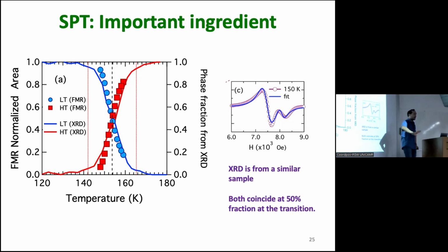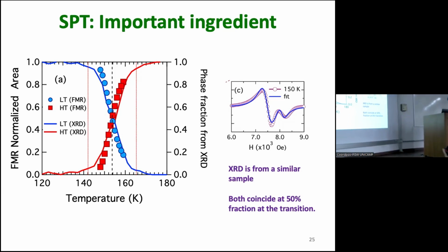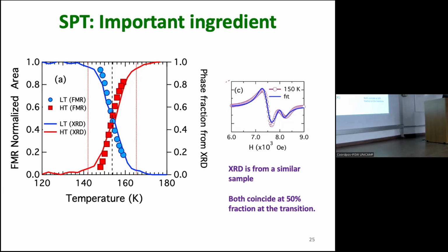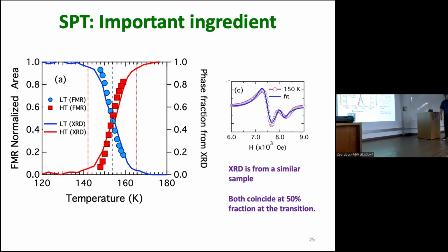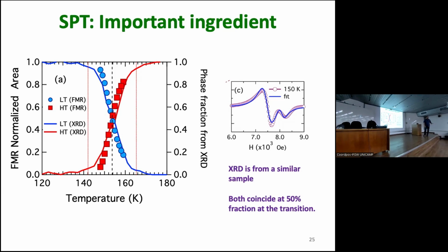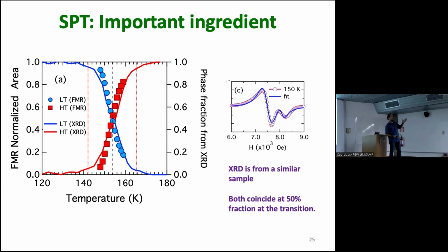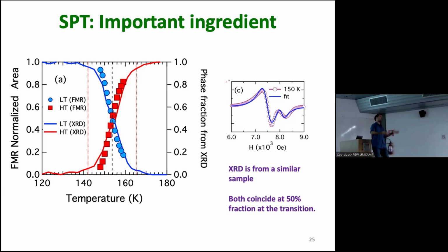So I can actually plot as a phase fraction. I will call this the high temperature phase and the low temperature phase. If I do the same at the same temperatures, but looking at the X-ray diffraction data, I can see how much is the proportion of the high temperature peak and the low temperature peak. And then I will know a structural, crystallographic phase fraction.